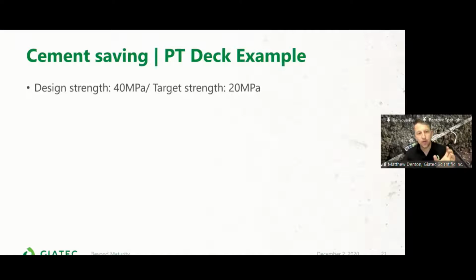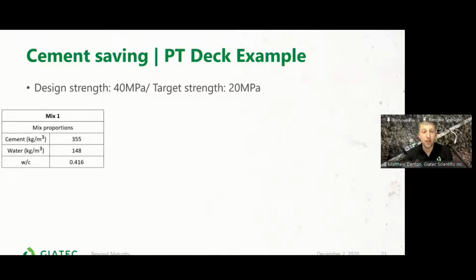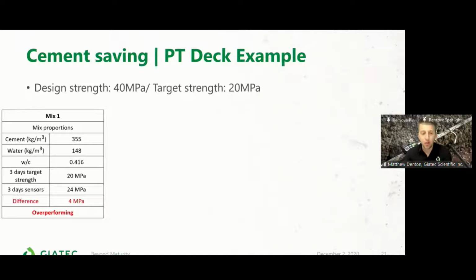So there was a design strength of 40 MPa. However, the target strength for the post-tensioning was 20 MPa. If we break this down, we look at mix one, we look at the mix proportions that we had: the kilograms per cubic meter of cement, the kilograms per cubic meter of water, and the water cement ratio. Fairly standard mix, not too complicated here. And when we look at the 3 days, the target strength that we had was 20 MPa. When we actually started reading the information from the concrete sensors, our Smart Rock sensors that were placed in the concrete, we realized that there was actually a 4 MPa difference between the target strength that they were aiming for versus the actual strength they were achieving on site.